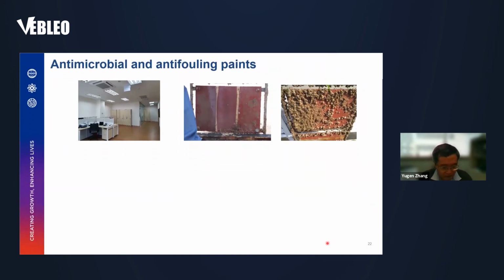And the same materials we can also use as antimicrobial ingredients for different paints. For example, we can just use them for wall paints for your office. And these materials can create a bacteria-free surface. And interestingly, this material can also degrade formaldehyde to provide a clean environment for you, especially in the room. And they can also be used as antifouling paints. Showing here is one example where the paints incorporate some of our materials, and there is quite a clean surface with no fouling. But without adding our materials, you can see a lot of material is attached on the surface.